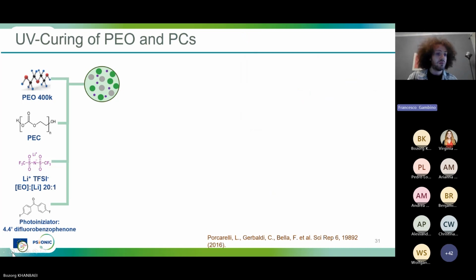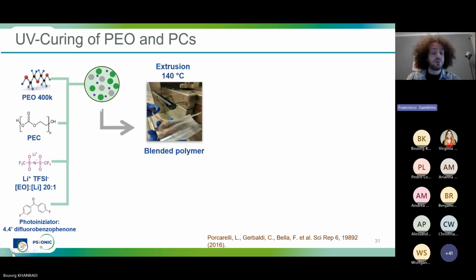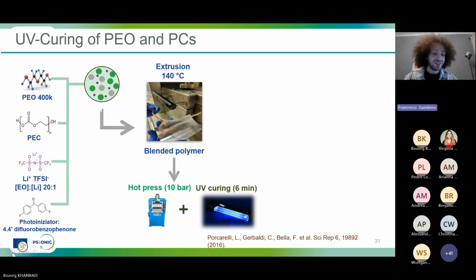So we tried to vary our process that we developed at the beginning, and we introduced a photoinitiator that is stable at the temperature of the extrusion. Next, please. So again, we produced the blended polymer, but with the inclusion of this photoinitiator. And next, please. We hot pressed the obtained blended polymer, and after UV curing with a UV lamp, we were able to produce a cross-linked polymer. Next slide, please.